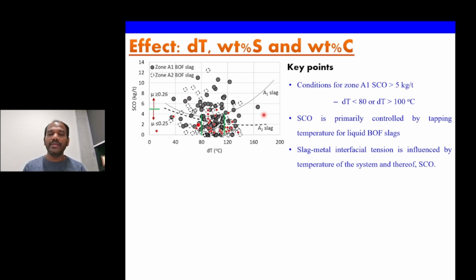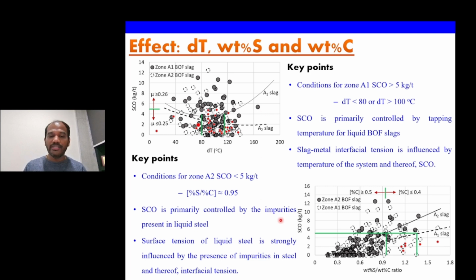This temperature can be indirectly connected to the interfacial tension. We all know that this interfacial tension plays a major role in bringing the vortex formation. And another inference from slag carryover is what we have plotted for all the heats with the sulfur to carbon ratio, because sulfur and carbon are interstitial elements present in the liquid steel, which can also bring some changes to the interfacial tension. And the conditions established here for the zone A2 slag carryover, BOF slag, for less than 5 kilogram per ton, the ratio needs to be 0.95.